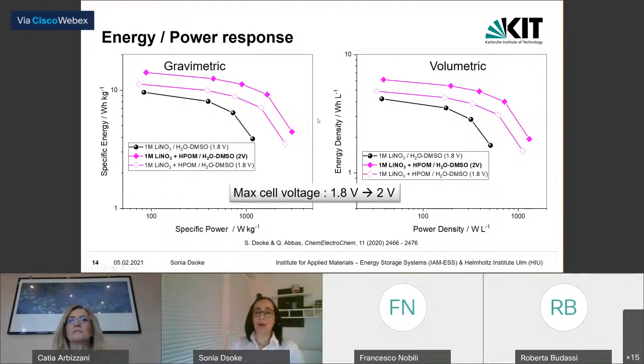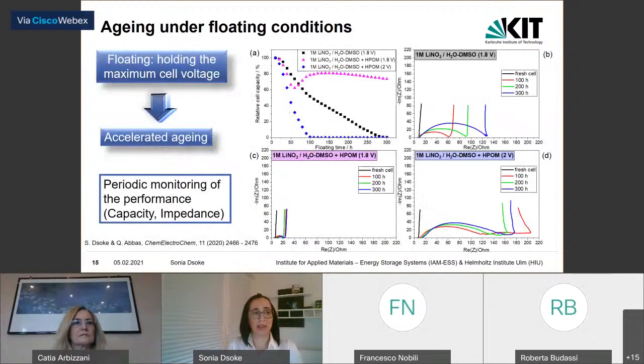However, it's very important to understand if the system under this condition, so 2 volt or 1.8 volt, is stable also for a long time. Therefore, we performed some accelerated aging, which was done under floating conditions. So floating means holding the system at the maximum cell voltage. For a supercapacitor, this is a way to perform an accelerated aging, because when we keep our electrode at the limit, at the maximum voltage, most of the parasitic reactions occur.